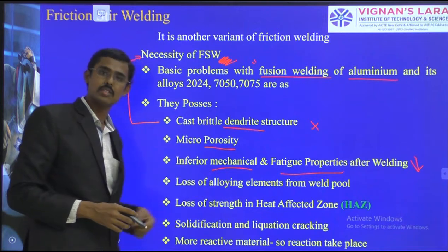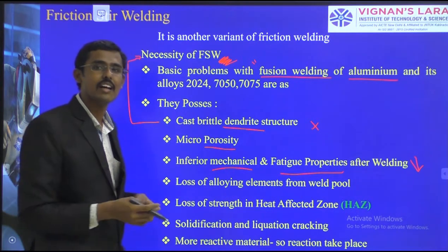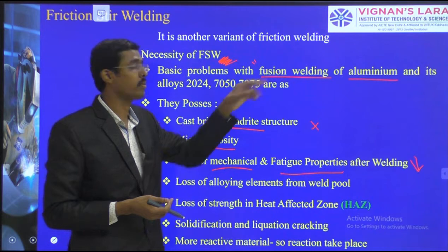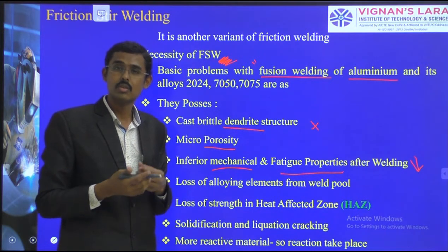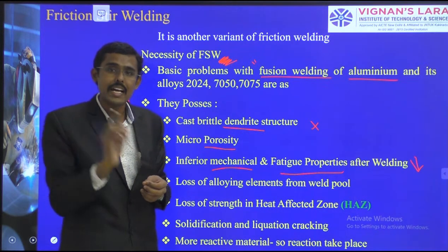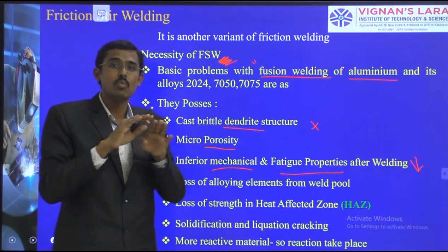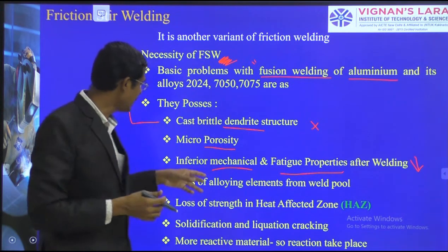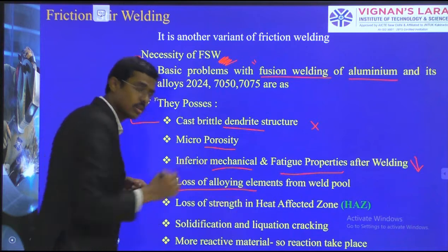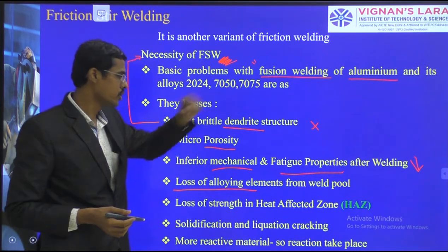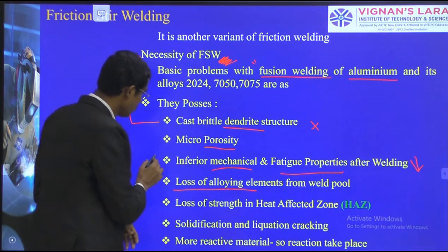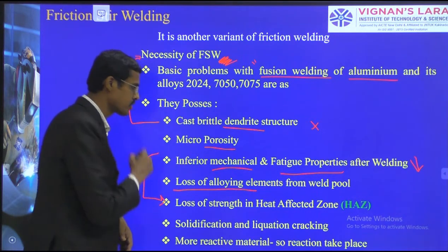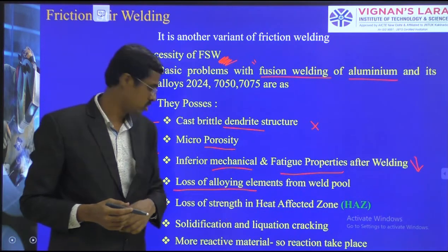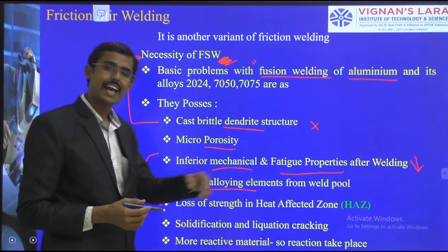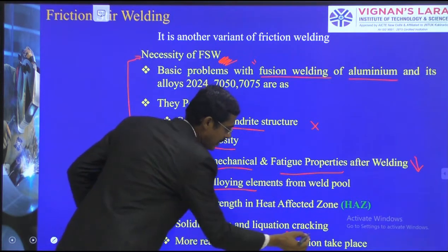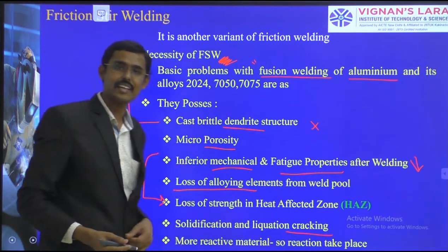Loss of alloying elements. Some of the alloying elements which are added evaporate due to the high temperature of the fusion welding process, so the improvement in mechanical properties that they were added for, we won't get. Loss of alloying elements also happens in fusion welding. Loss of strength, inferior mechanical properties, loss of strength in the heat affected zones. Solidification and liquation cracking: the dendrite causes cracking.